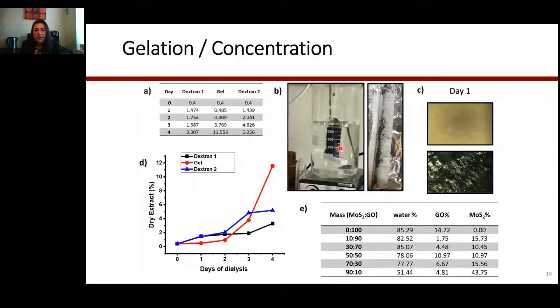The problem is that I had just 3 months in France. I couldn't spend 1 week to just obtain one gel. So the first novelty of our process was using this absorbent gel, where we cut the time to about 4 days for some of the materials, and some of the materials I was able to obtain in under 2 days, as you can see here in the bottom.